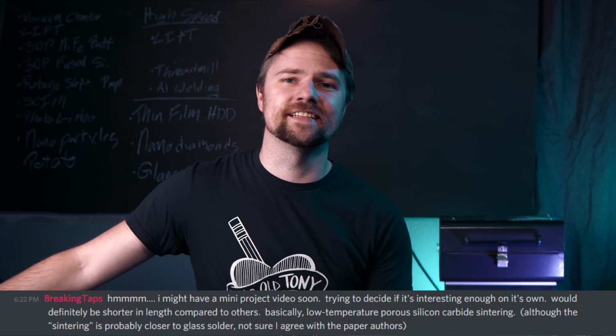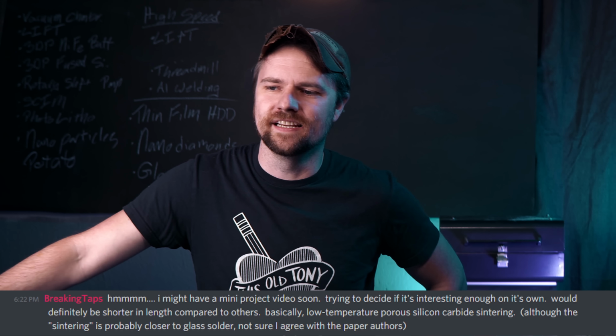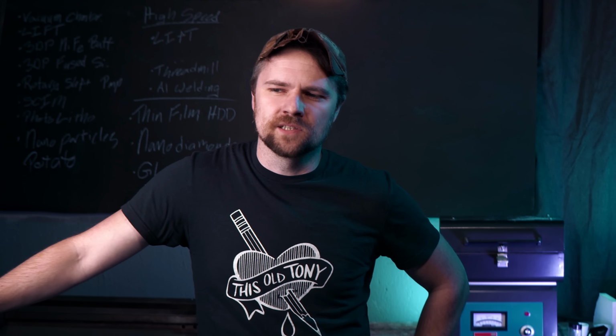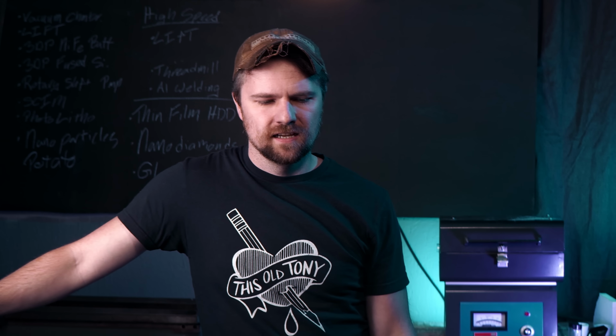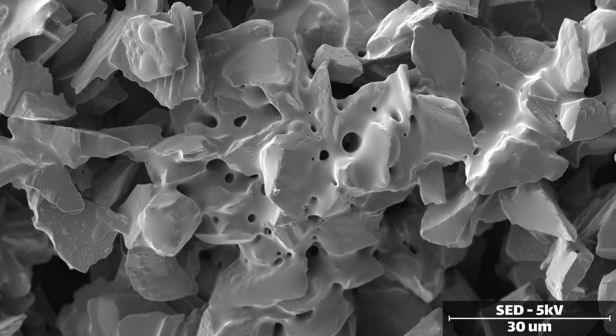I wanted to, I really did, believe me. I wanted this to be a quick and easy video. But something was just nagging me while I was looking at the images and collecting some more scanning electron micrographs. And it was the kind of liquidy looking interface between the silicon carbide grains. Because of the explanation that there's a thin oxide layer on all these grains and they get joined together to form little glassy bridges. And that's helped by the borax fluxing agent. But it looked like an awful lot of glass in between these grains.